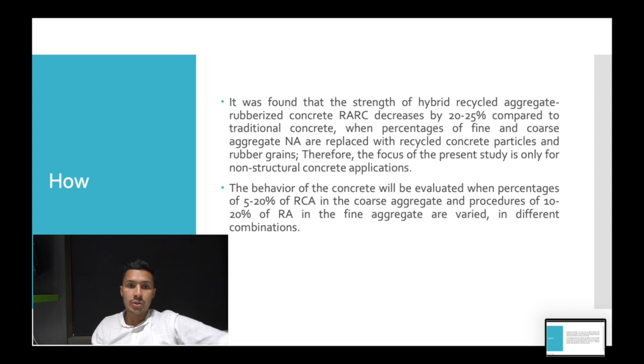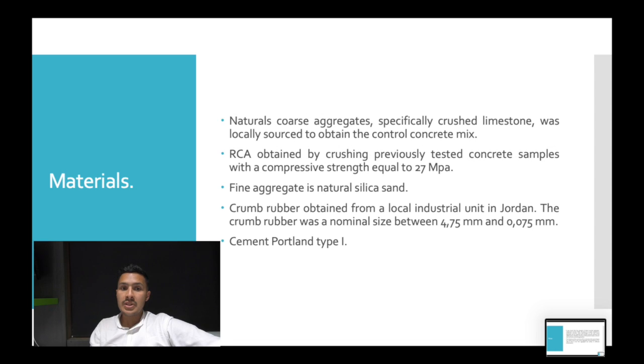Below, the evaluation of the response of the material is shown, replacing 5 to 20% of the granular material with recycled concrete and 10 to 20% of the thin material with ground rubber, used in different combinations. The granular material is a limestone recycled concrete with a minimum strength of 27 megapascals. The fine aggregate is a natural silica sand, ground tire rubber, and Portland cement type 1.